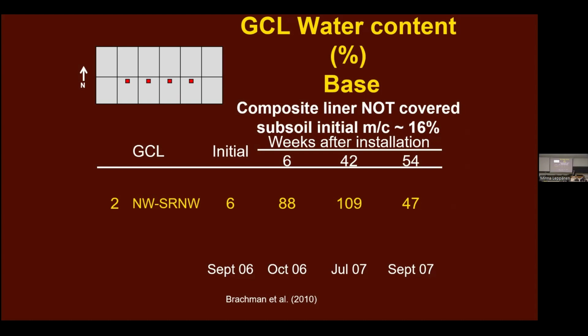its history. And so here are 2 examples of GCLs. The first one, GCL2, had an initial water content off the roll of 6%. And in the field, after 6 weeks, it had hydrated to 88% gravimetric water content. After 42 weeks, it was 109. And this is fully saturated at 125. So it was hydrating very nicely. And then at 54 weeks, it's at 47. So what is going on here?